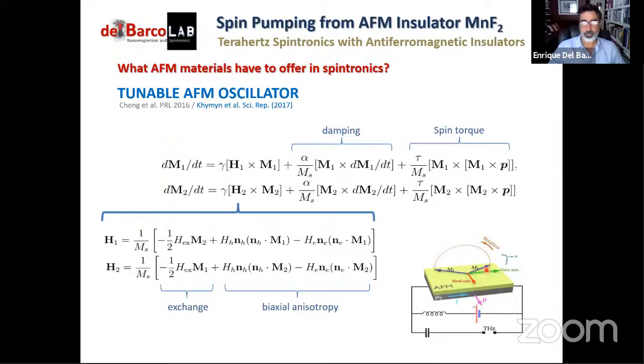This is described by these two coupled LLG equations, where you have a first term that couples every sublattice magnetization with the other one through H1. So M1 and M2 are coupled here in this fashion, and the same thing for the other sublattice magnetization. Then we have the anisotropy, in this case a biaxial easy-plane anisotropy system. Then we have the Gilbert damping, characterized by the Gilbert damping parameter. And that is one of the reasons for which we use insulating antiferromagnets, because damping is substantially smaller than in conducting antiferromagnets. And then we have the spin torque term, and that is basically the coupling of the spin polarization from the spin current to the two sublattices.